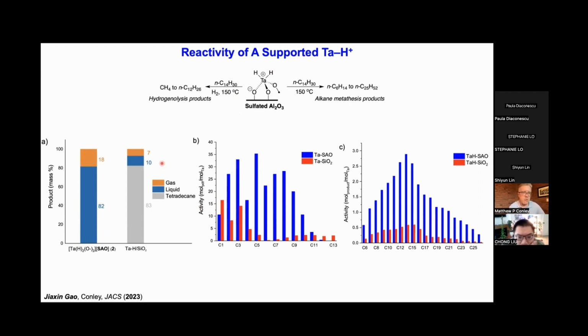If we compare that directly under the same exact conditions using tantalum hydride on silica, we convert significantly less tetradecane, and we get a completely different distribution of products out of the hydrogenolysis reaction. One of the unique features of the tantalum hydrides that distinguishes them from zirconium hydrides is their ability to catalyze the metathesis of alkanes. The metathesis of alkanes involves dehydrogenation and alpha elimination steps to generate alkylidenes that undergo olefin metathesis and subsequent hydrogenation reactions to generate a distribution of alkane fragments.